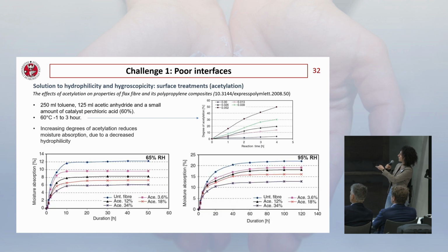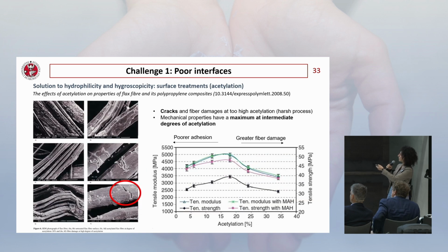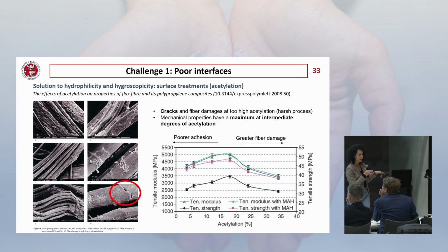So if you use too little acetylation, you will end up with a poorer adhesion, so the mechanical properties will be low. If you use too much acetylation, you will degrade the mechanical properties of the fibers and the surface, and therefore you will end up with a composite with lower mechanical properties.